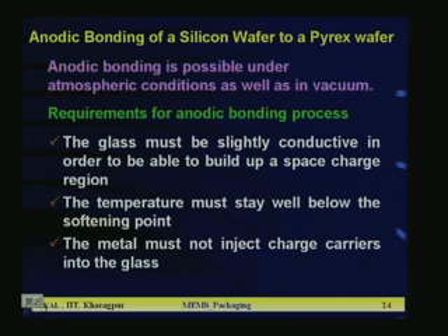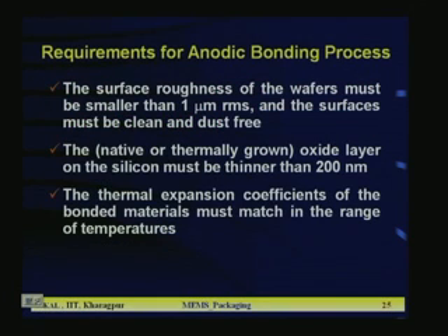Second requirement, temperature must stay well below the softening point. Third, the metal must not inject charge carriers into the glass. If there is metal on the surface or in the silicon, those metals must not inject any charge carriers into the glass, that is another requirement. Others are, surface roughness of the wafers must be smaller than 1 micron RMS. In the case of fusion bonding it was 10 angstrom RMS if you remember, but here roughly 1 micron RMS is also okay. The surface must be clean and dust free. The native oxide layer on the silicon must be thinner than 200 nanometer, means 2000 angstrom. The thermal expansion coefficients of the bonded materials must match in the range of temperatures.